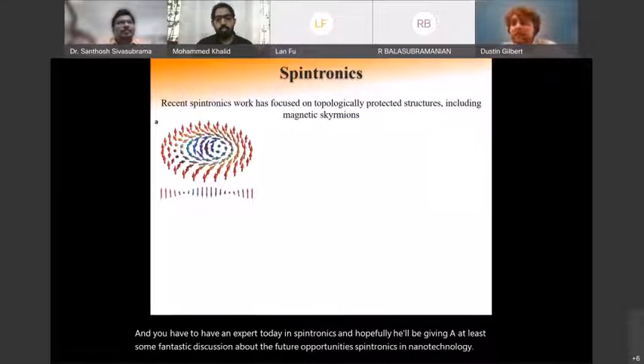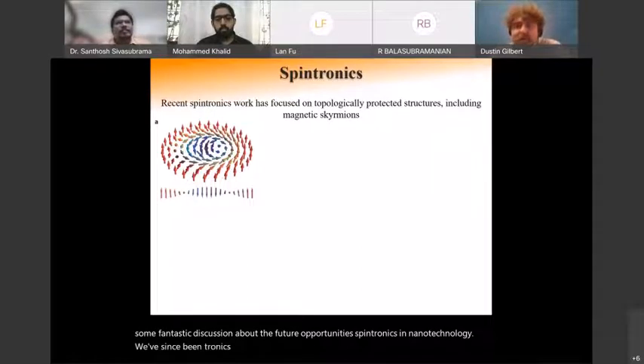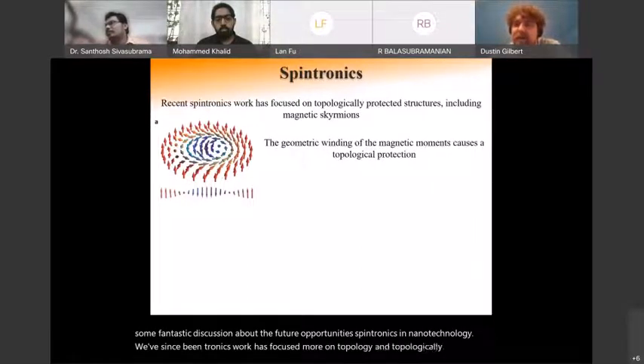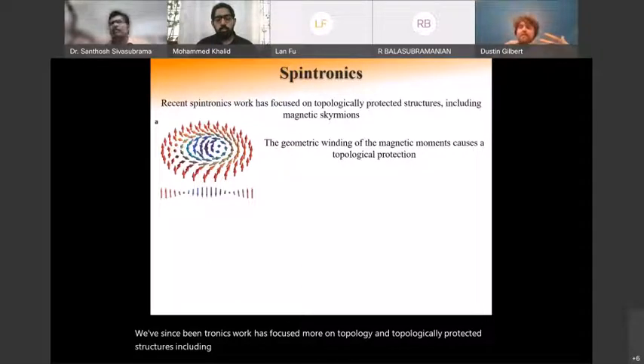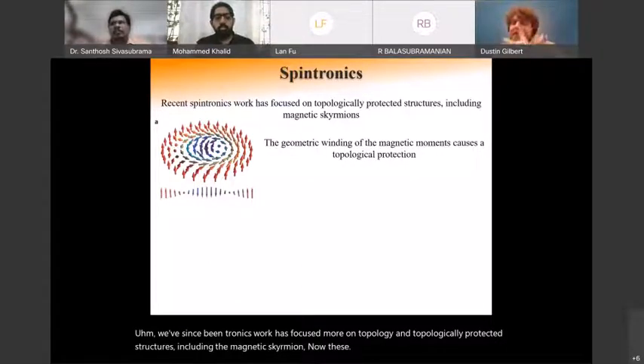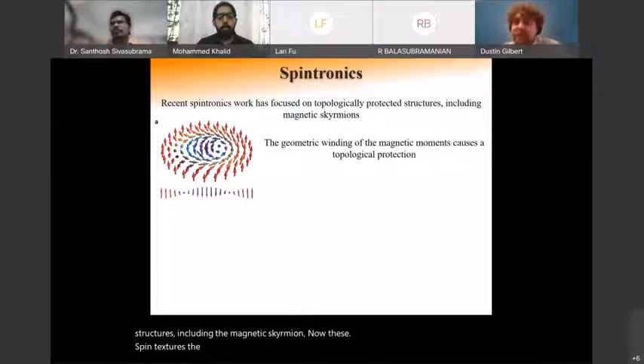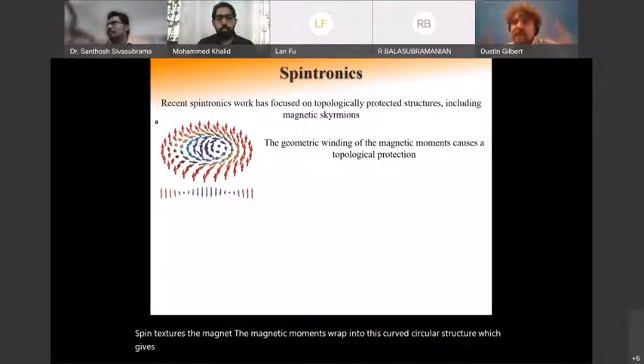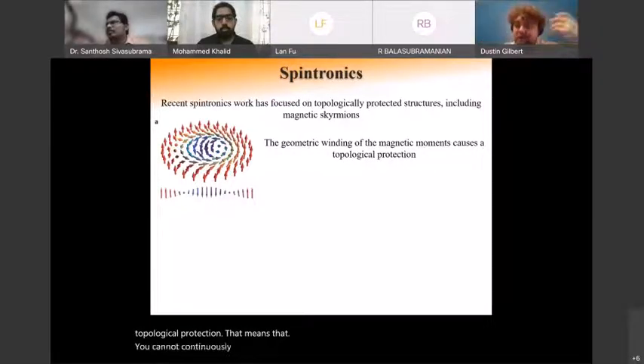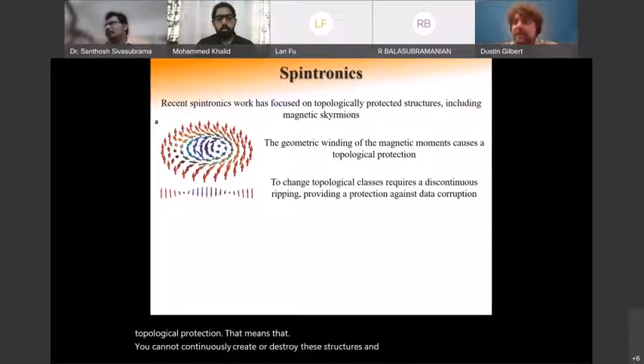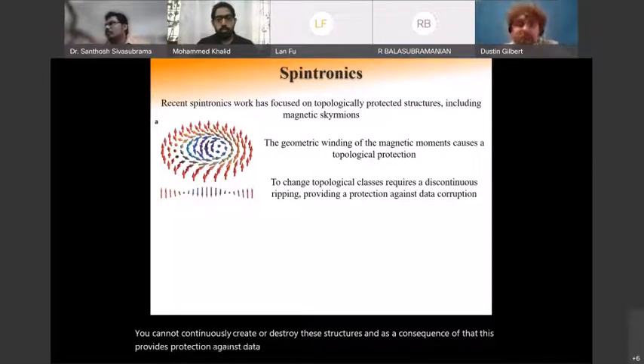Recent spintronics work has focused more on topology and topologically protected structures, including the magnetic skyrmion. Now in these spin textures, the magnetic moments wrap into this curved circular structure, which gives it a topological protection. That means that you cannot continuously create or destroy these structures. And as a consequence of that, this provides protection against data corruption. And so there are possibilities for that.